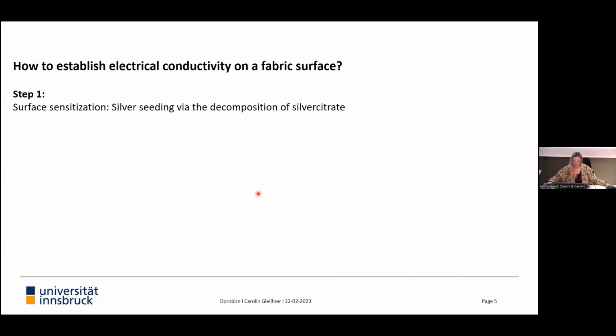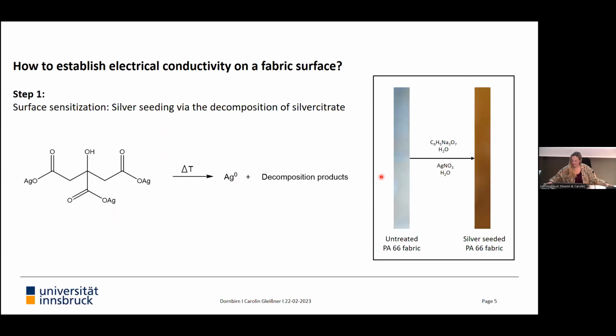To go a little bit more into detail, like I said, we do the silver seeding via the decomposition of silver citrate. If you first immerse your fabric in sodium citrate, dry it, then immerse it in silver nitrate, and dry it again at elevated temperature, then silver citrate is formed at elevated temperature. Silver seeds are formed, and this is how it would look on the fabric. You have this white polyamide 6/6 fabric, and after the silver seeding, you get a light brownish color on the fabric.